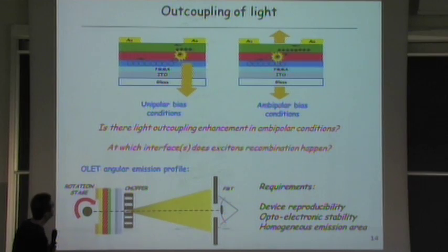Okay, now the questions here were, is there light outcoupling enhancement in ambipolar condition, and at which interface or interfaces does exciton recombination happen? To answer the first question, we used our homemade setup. It's very easy. We have a rotation stage with a sample holder on top. We use a light chopper to increase the signal-to-noise ratio because it is connected to a lock-in amplifier. And in front of it, there is the photomultiplier tube.